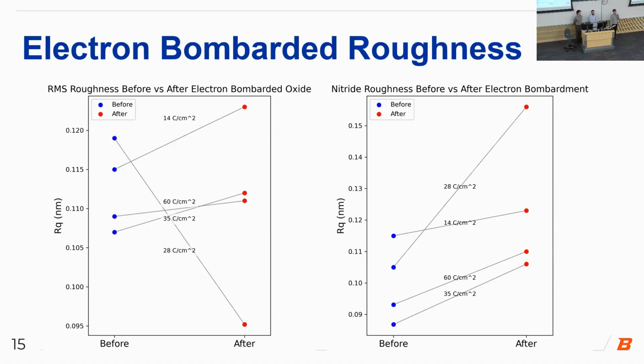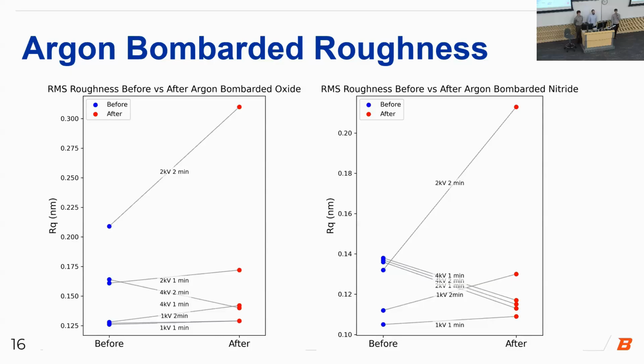The noise floor of the instrument and the mode of contact that we did for attaining this data is around 50 picometers. And as you can see on the axes, on the y-axis, our scale is in the hundredths of nanometers, which is within the noise floor of the instrument. So with regards to electron bombardment and argon bombardment, there is no significant difference in roughness pre and post processing on our samples.